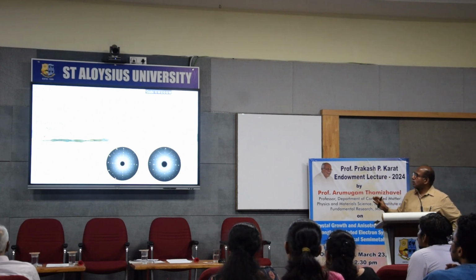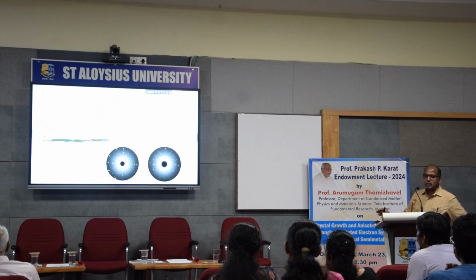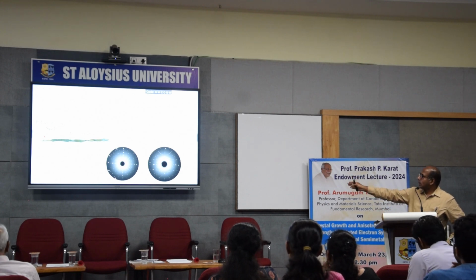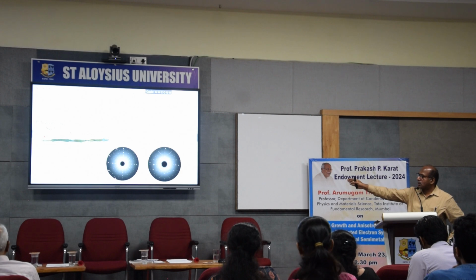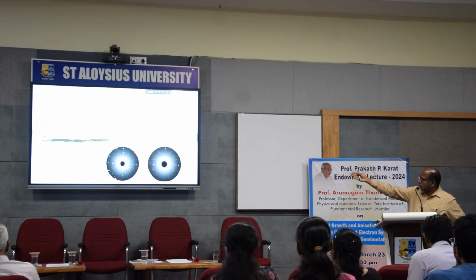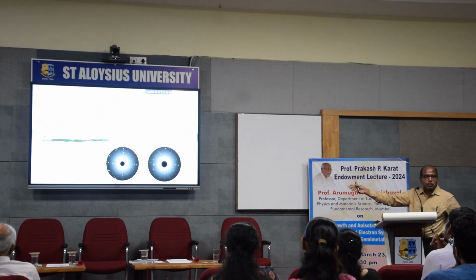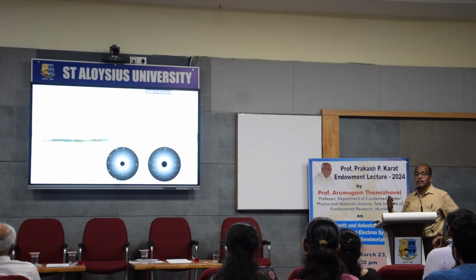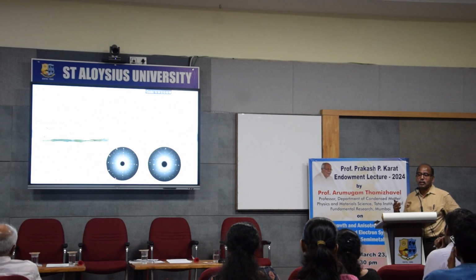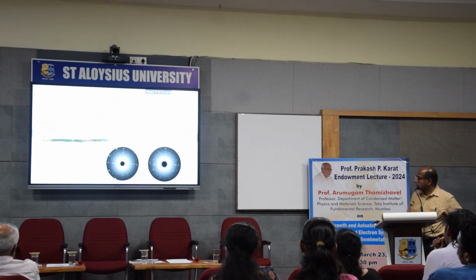This compound crystallizes in a tetragonal crystal structure, and this is along the A axis and that is along the C axis, the Laue diffraction pattern. We have found a beautiful Laue diffraction pattern. Just by looking at the Laue diffraction pattern itself, I can say that the crystal that I have grown is of the highest quality. The quality of the crystal is extremely good.